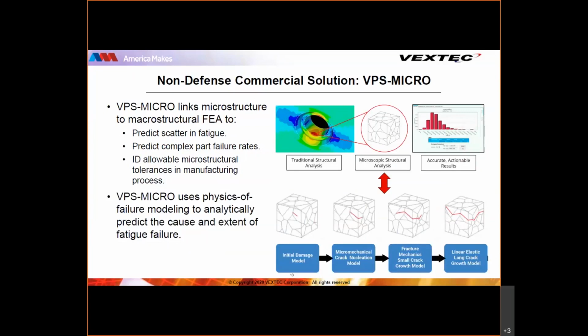So VPS-MICRO takes the traditional FEA-based structural analysis and superimposes at the elemental level the microstructure of the material to predict the statistical distribution of fatigue cycles to failure. And to do this, the software simulates the damage accumulation process, starting at the initial crystal plasticity to nucleation of a crack, to small flaw fracture mechanics, to linear elastic fracture mechanics. So it follows that process through its various stages.